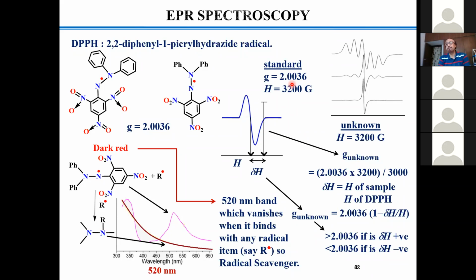So what I am trying to convince you is that the g value is extremely important to assign whether your singly occupied molecular orbital is metal based or ligand based. Now I told you that conventionally 99% of ligand systems don't exhibit much radical character. They are mostly anionic or neutral. And in that case, if you have a transition metal based compound, you will see the g value is always 2.x, 2.1, 2.2, 2.3, whatever it is. So it is purely metal based. But for a set of ligands, I said quinones and a few other ligands, variable oxidation states are possible. They are called redox active ligands.